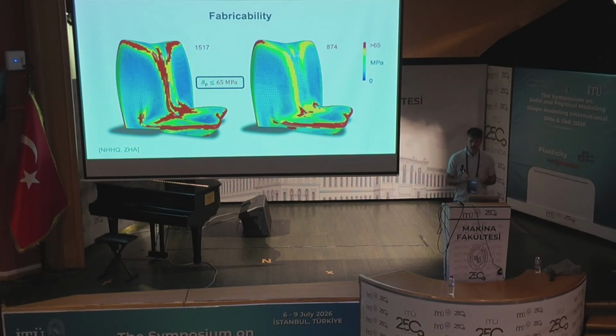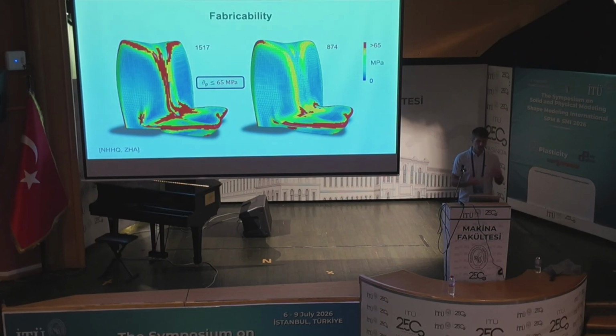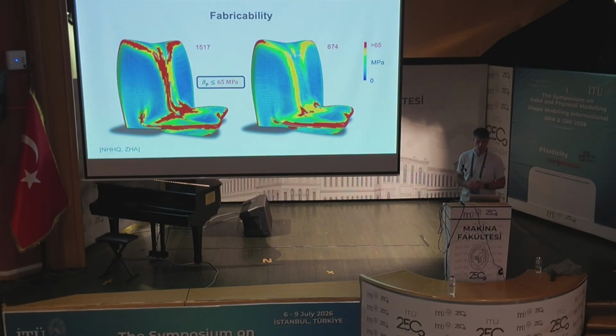By optimizing the design for fabricability, for example, by slightly adjusting the shape, in this specific example, one can drop the number of breaking panels, or panels that would need to be made from hot bending, from 1,500 to 900, while still staying, I'm not sure if the designer agrees, reasonably close to the initial shape. This results in approximately a 40% reduction of the number of panels that would otherwise need to be hot bent, and therefore allows for much more economic fabrication.